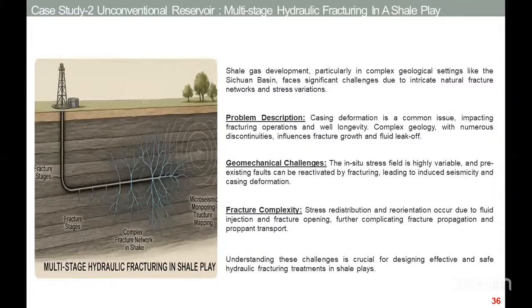This is case number 2, for the unconventional reservoir: multi-stage hydraulic fracturing in a shale play. In this shale play, complex fracture networks and variable stress contribution pose a challenge for stimulation. The problem is casing deformation during fracture operations and well longevity. Complex geology, discontinuous influence, fracture growth and fluid leak-off. A geomechanical challenge is also that the in situ stress field with pre-existing faults can be reactivated by fracturing, leading to induced casing deformation. This is the main problem, along with fracture complexity, stress distribution and reorientation, injection and fracture opening, further complicating fracture propagation and transport. Understanding these challenges is important for designing effective and safe hydraulic fracture treatments in shale plays.